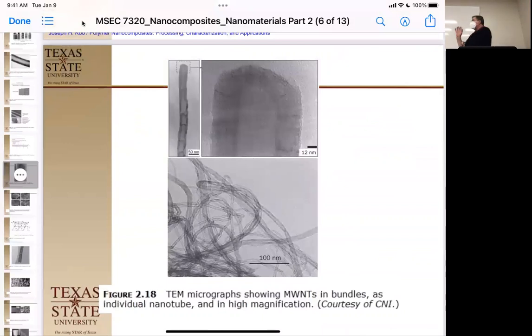Okay, so now we've moved on to the one-dimensional, which has one axis. Typically there's a very long axis outside of the narrow range that goes for those fibers, and the length of those fibers gives you different properties. Like let's say you have a long conductive multi-walled carbon nanotube. That is going to give you a different level of loading required to get a desired change in electrical conductivity than a shorter length.